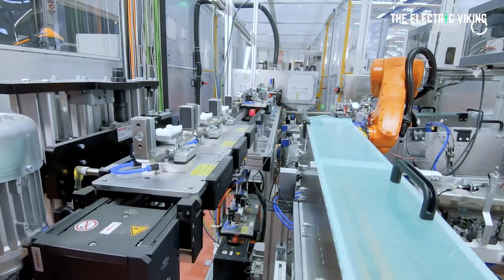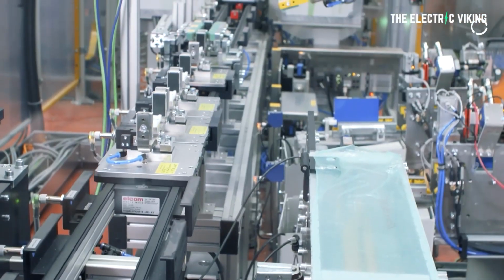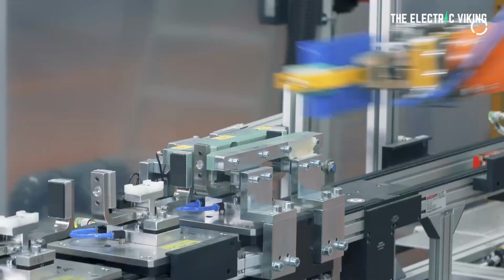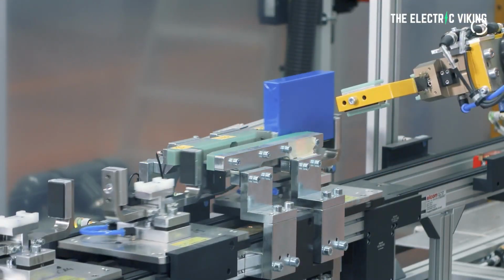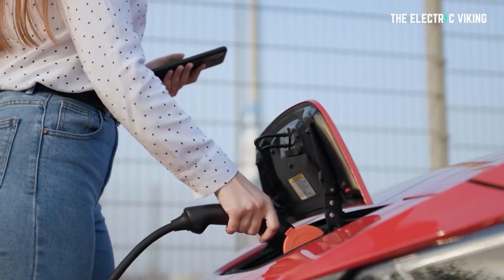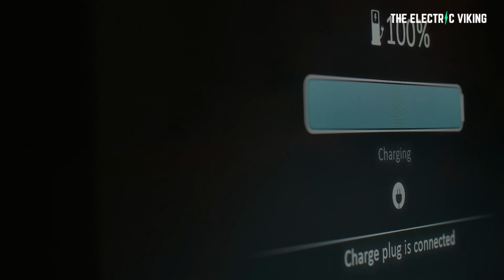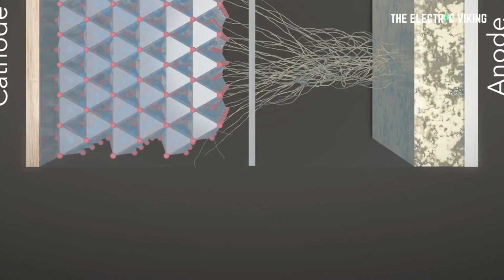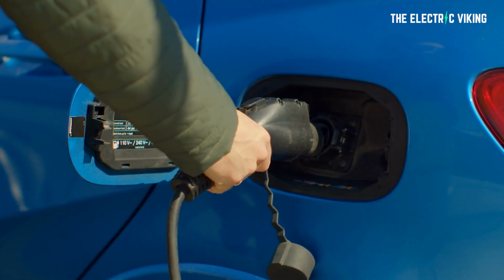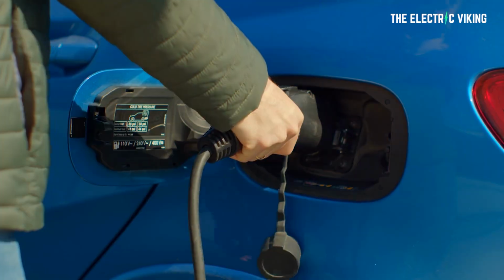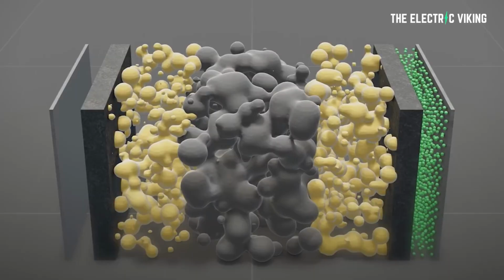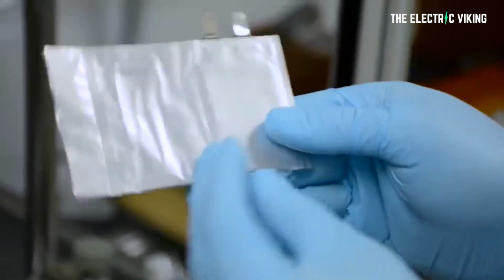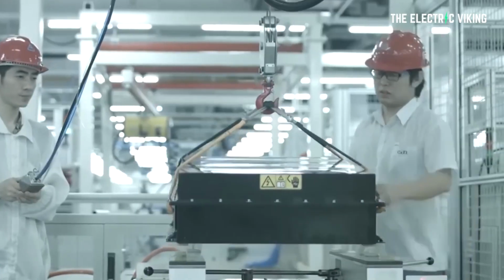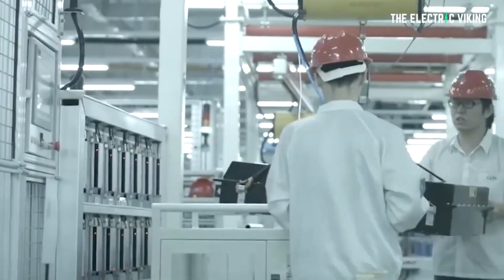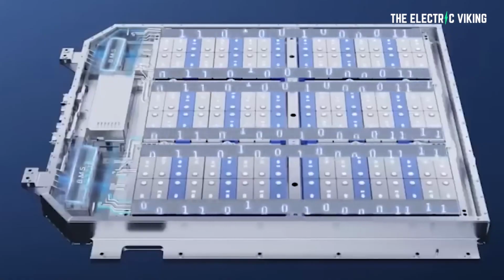The team discovered that the THNS-based lithium-ion anode could sustain extremely high current rates in the order of 15 to 20 amps per gram, enabling ultra-fast charging in approximately 9 to 14 seconds after 10,000 cycles under the high current rate. Capacity retention greater than 80% was observed. In other words, what this means is that fast charging with this anode in a lithium-ion battery enables these battery packs to be charged 10,000 times and still have 80% of their original capacity.